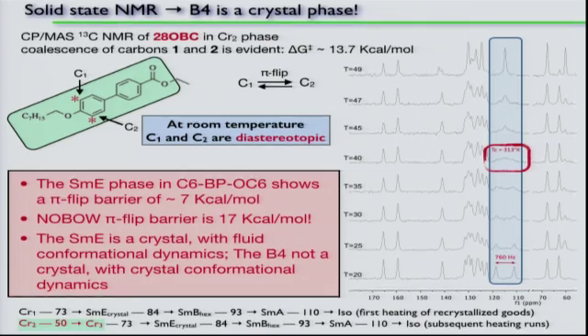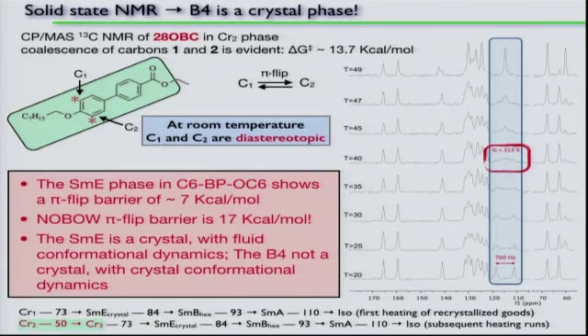But we looked at a really low temperature smectic E. Well, it doesn't have to be low temperature. We looked at a smectic E that, well, it was at 2 degrees. It transitioned into a crystal, and I guess I don't have the details of that. But looking at another smectic E that we could cool down more in the smectic E phase, you see broadening. You never see two peaks, but you see broadening. And by analyzing the peak shape, you can calculate a 7 kcal per mole barrier for a smectic E. 7 kcals, and the rate is kind of exponential with the barrier height. So 7 kcals is much faster.